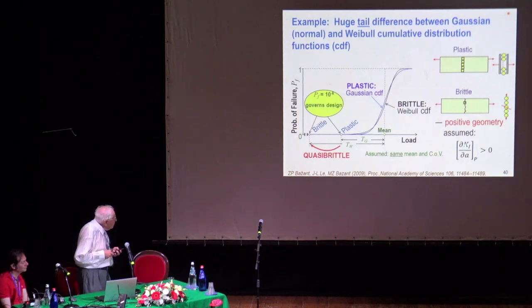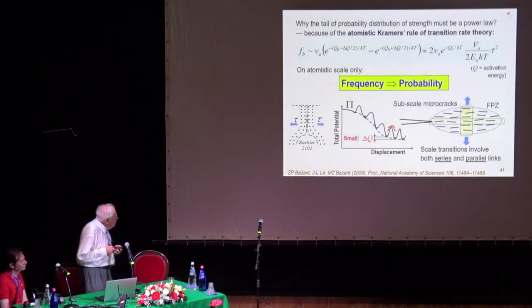Of course, it assumes that the field is a positive geometry in this case. Now, the type of distribution for brittle failures should be determined not from flaws on the mesoscale, which is correlated, of course, but is going from one assumption to another, but should be done more fundamentally from rupture of interatomic bonds. This is Kramers' rule of transition rate theory in chemical thermodynamics.